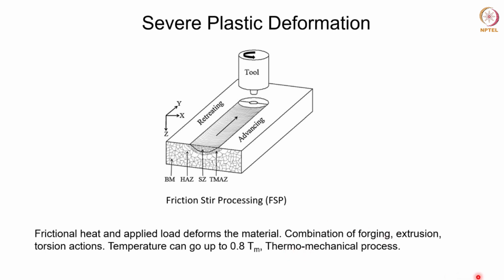So as I said, this is the stir zone which is subjected to severe plastic deformation. So this will have a fine grain size. But apart from this stir zone, there are other microstructural zones having very definite microstructure around it. For example, just adjacent to the stir zone, you have a zone known as the thermomechanically affected zone, or TMAZ. So this zone also is subjected to high temperature and deformation, but the degree of deformation here will be lower compared to the stir zone.